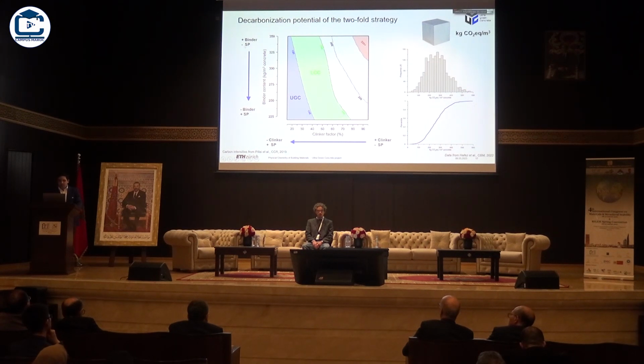And what would be the clinker factors and the binder content that would enable me to get into those ranges? We can see, for example, that if we take the average value, which at the moment in this data set is 250, and then we take the best 15%, we can set one limit for low carbon content, let's say 160 kilograms per cubic meter. And this is a range that we can easily access with LC3. So if we use LC3 50, we can produce low carbon concrete out of the box with almost any binder content that you want. This is assuming a worst case scenario for clinker, so if you improve your clinker as well, that opens the gate. But the ultra green concrete project is a little bit more ambitious, and we propose to develop technologies to enable making concrete with less than 100 kilograms of CO2 per cubic meter.